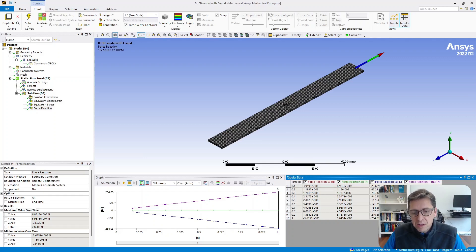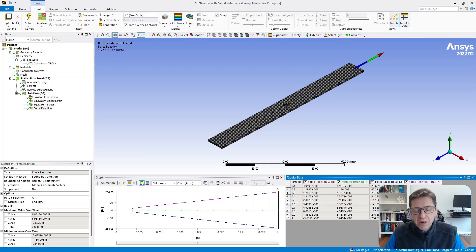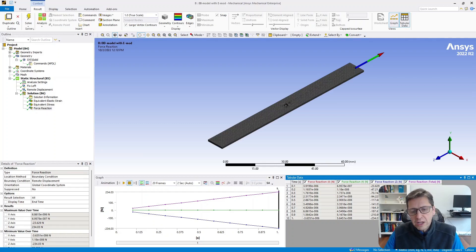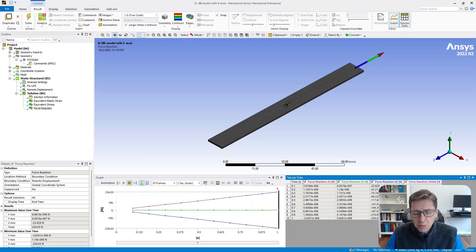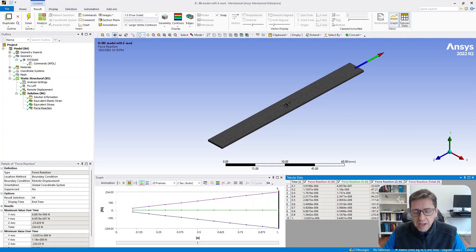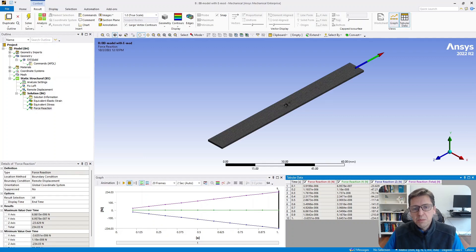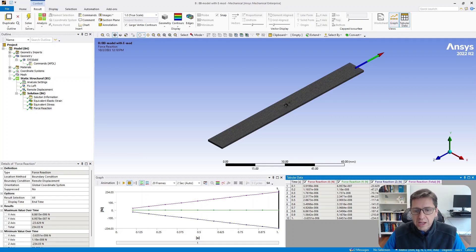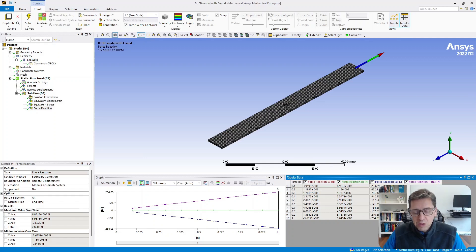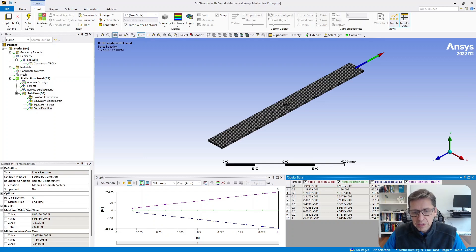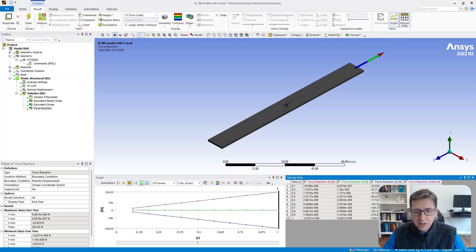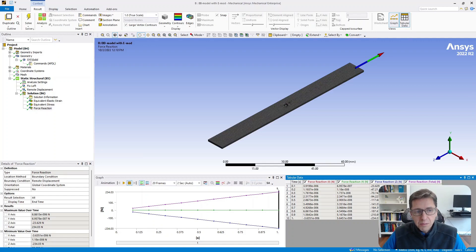And so what did we learn here? The key lesson is that when you calibrate the material model, don't forget the Young's modulus. Don't forget to make sure that you have a good prediction of the Young's modulus too. And you can do that in MCalibration by adding a load case for the Young's modulus. And often I add one load case for the Poisson's ratio as well. But the Young's modulus is something that people don't always remember to keep track of. And then you can have very poor predictions, as I showed here. If you have any questions, you can ask them below. Thank you.